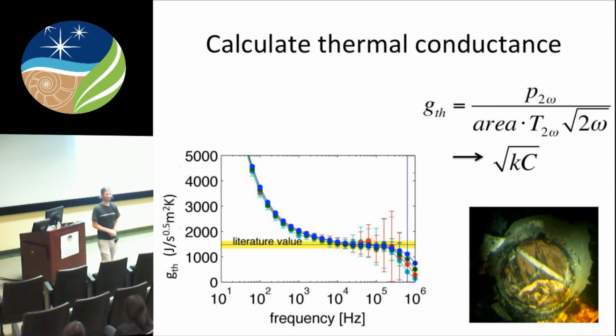What was your first question again? Independent method of determining temperature from the sample chamber. Is there any? There's not many. Because I put a ruby in to measure pressure, assuming I know the temperature. I vary the cryostat temperature slowly so that I know the temperature at the surface of the diamond cell. If I wait for long enough, I'm confident in those values.